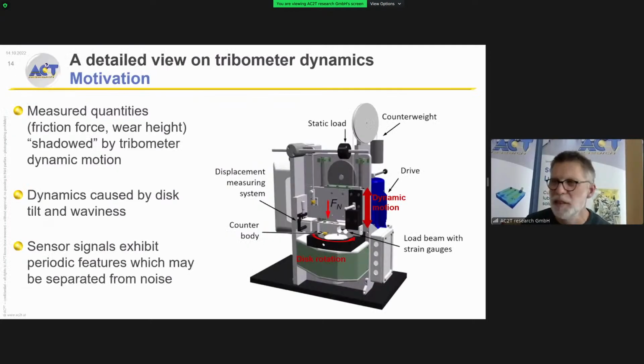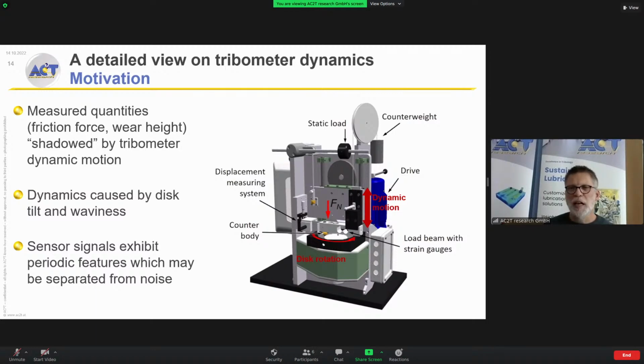of the machines themselves. So if you look at a typical, this is really a prototypical tribometer, is a pin-on-disc tribometer which has a rotating disc, and a pin which is pressed by a loading mechanism against this rotating disc. And then you have typically a force measurement which is measuring the normal force and the friction force using, for example, a cantilever or other system. You often also have some kind of displacement measuring device which would give you an indication about the total wear which you have already produced.